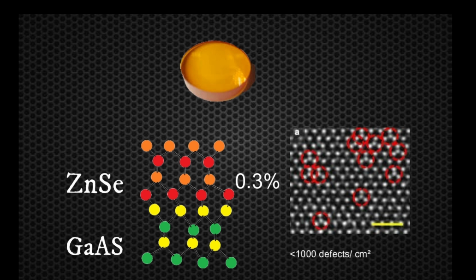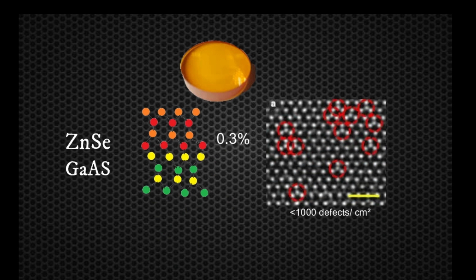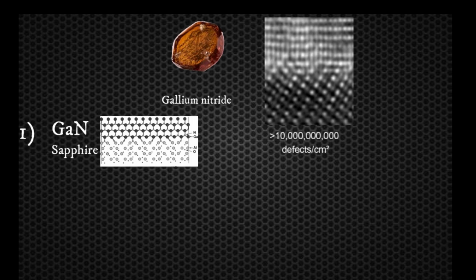Its only issue was that while scientists had figured out multiple different ways to create N-type zinc selenide, no one knew how to create P-type. In contrast, gallium nitride had been abandoned by almost everybody for 3 reasons. First, it was much harder to make a high-quality crystal. The best substrate for growing gallium nitride was sapphire, but its lattice mismatch was 16%. This resulted in higher defects, over 10 billion per square centimeter.